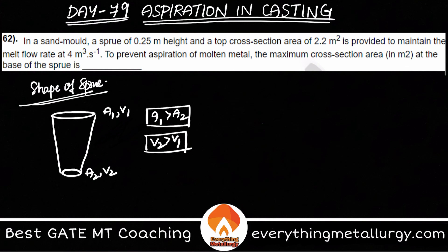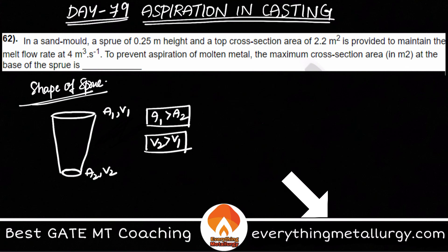What happens is the metal will flow with higher velocity as it comes down, and whatever gases are absorbed can easily escape out. This is also called a pressurized gate. The area as we go along the sprue should come down, and the gate area should also be lesser compared to the sprue so that it will be pressurized with higher velocities. To avoid aspiration, you actually need to give some taper — a little taper from the vertical.